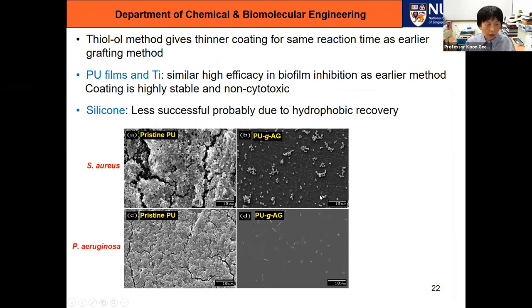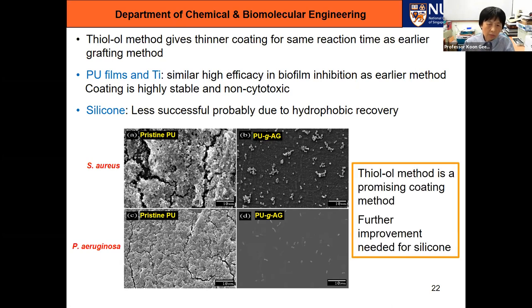The coating is non-toxic, but it is less successful for silicone. And we think the reason is because of hydrophobic recovery. The silicone chains are quite mobile. So if the coating is not cross-linked enough or is too thin, then the hydrophobic chains can migrate back up to the surface. So while this thiol method is promising, we need to improve it more for silicone, which is a very important biomaterial.